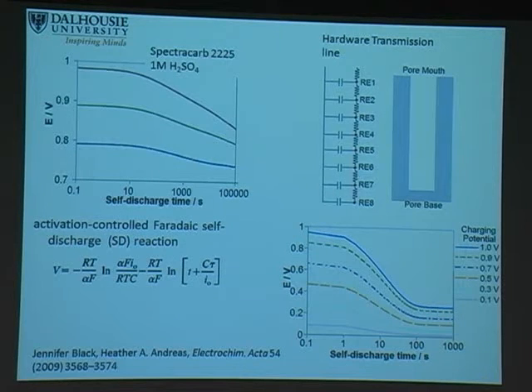What was surprising, and what caused more difficulties than we had hoped, was when we plotted these profiles as a function of log time. And what we see is a plateau and then a linear drop in potential. And that was exactly the profile that we were using to say something is an activation control process, because up until this point, it was believed that if you had a profile that looked like this, you had an activation controlled mechanism. And so what this now told us is that this isn't a diagnostic for activation control mechanism for porous electrodes. For porous electrodes, it can also be charge redistribution.